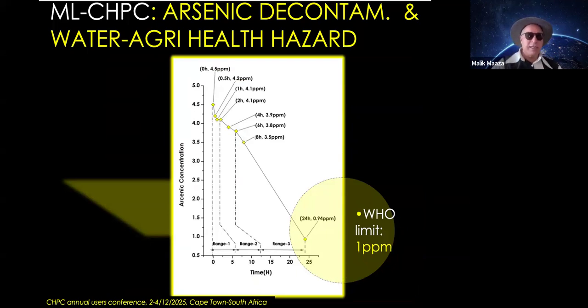So as you can see, you take water contaminated with arsenic, a standard solution, and you take your copper mesh which has been sulfurized to have the structure that I showed you before. That is this one. And when you expose that standard solution of arsenic, after 24 hours you remove nearly all the arsenic.